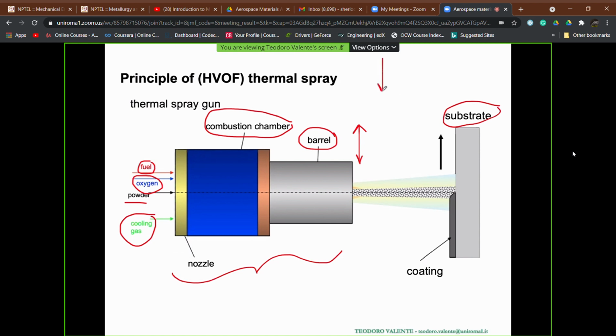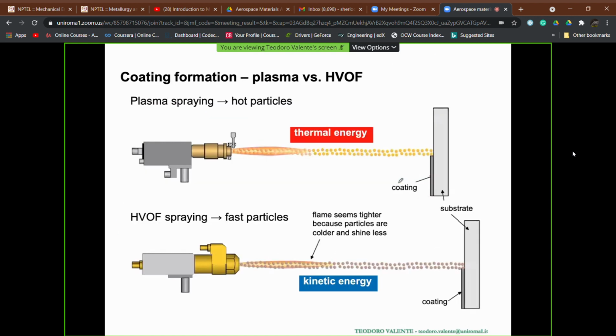This process, the HVOF, is a process which is carried out only in air. So one thing that we should discuss a little bit is the fact that if we are going to spray metallic-based materials, we could expect, in principle, due to the fact that we have air surrounding our flame, our plume, some kind of oxidation. But we will see that this can be very, very minimized for reasons that we will discuss in a moment. Remember that if we want to compare the plasma with the HVOF, we have said that the plasma processes, due to the high temperature, are essentially in all the variants controlled by thermal energy.